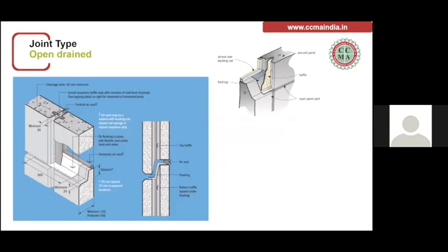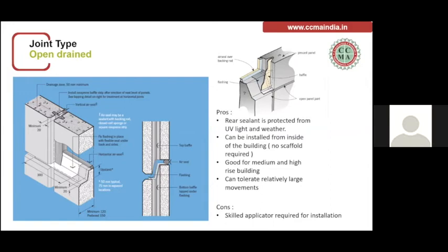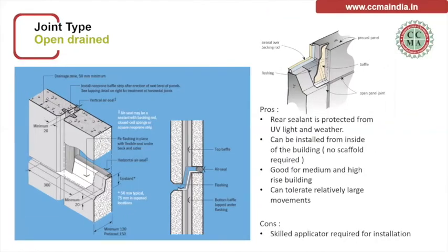Third type is open drain. Here, one provides a baffle which may be made of neoprene or PVC, which is loosely fitted in the expansion chamber, and when the water hits the baffle, it drains over the baffle. And for the inside, you provide a sealant which also acts as an air barrier. Advantages: the rear sealant, which is applied from the interior, is protected from UV light. This can be installed from inside of the building, it is good for medium and high-rise buildings and can tolerate large movements. Disadvantages: skilled applicators are required for installation.